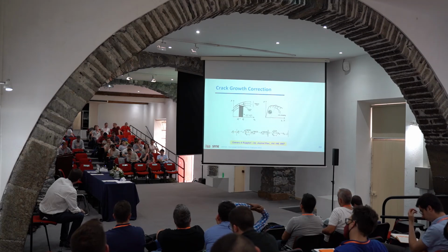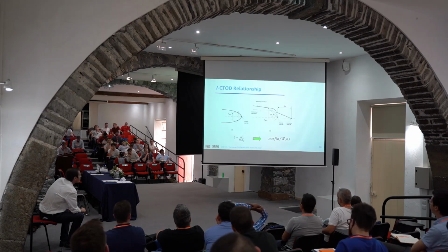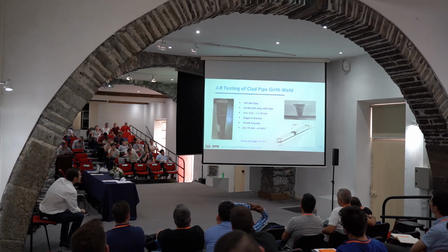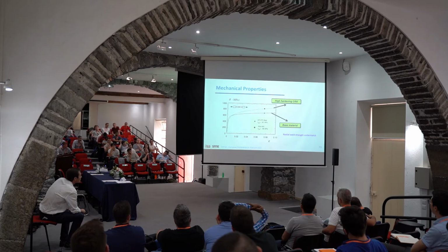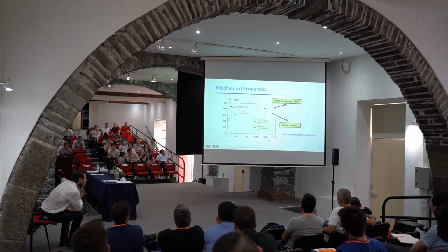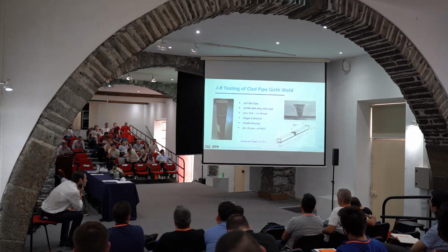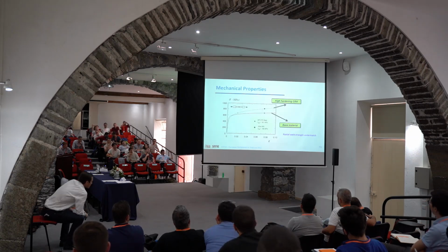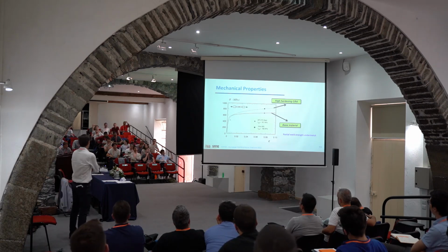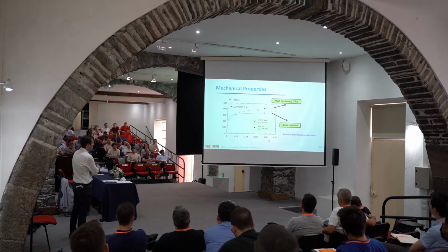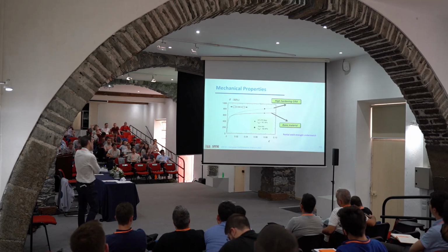But usually we don't perform a physical crack growth measurement, only at the end of the test. At the end of the test, we break the specimen and we measure. Just to show you some data, as I mentioned, the undermatch. This is an X65 pipe clad with Inconel 625, and that's the stress strain behavior here. The Inconel alloy has higher hardening but lower yield stress, and the base plate material, the X65, has higher yield stress and lower hardening. So you see that the mechanical behavior is different, and this will impact the assessment.